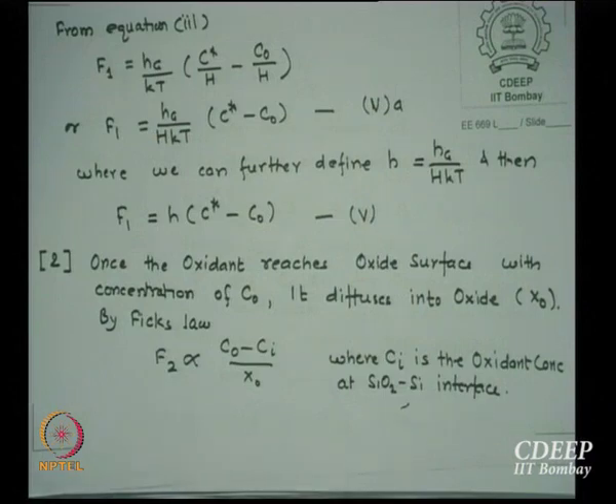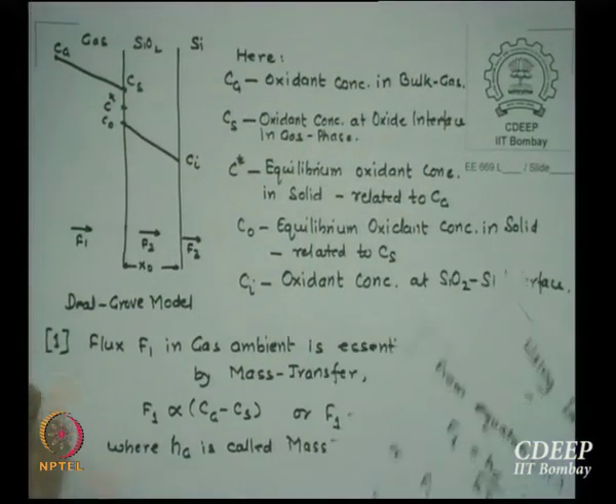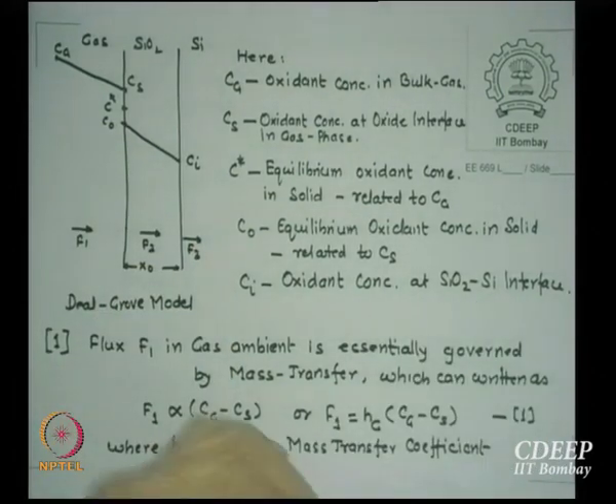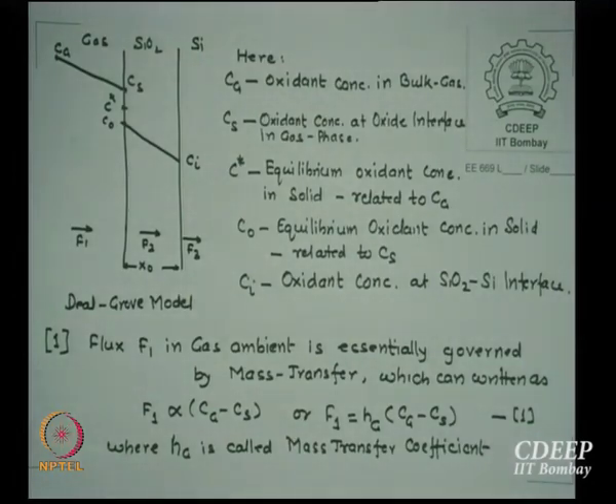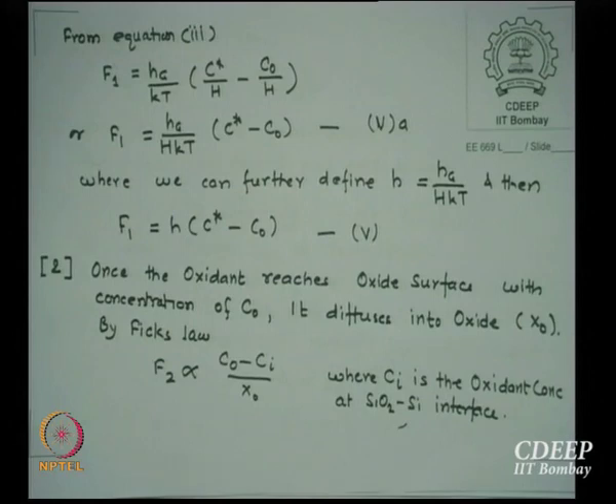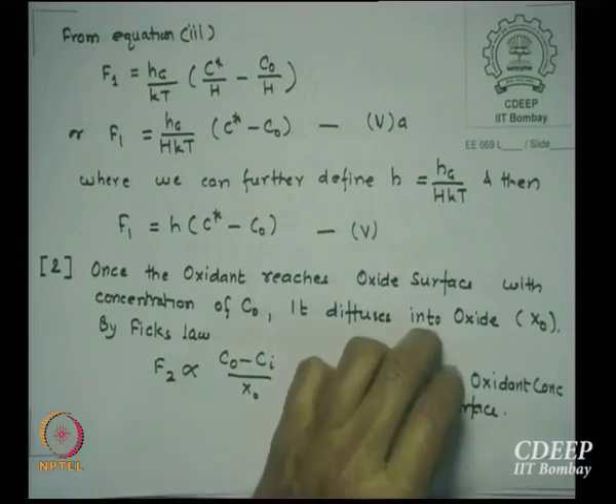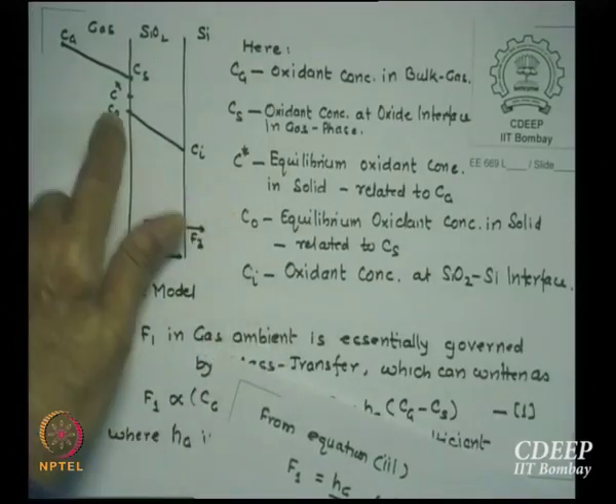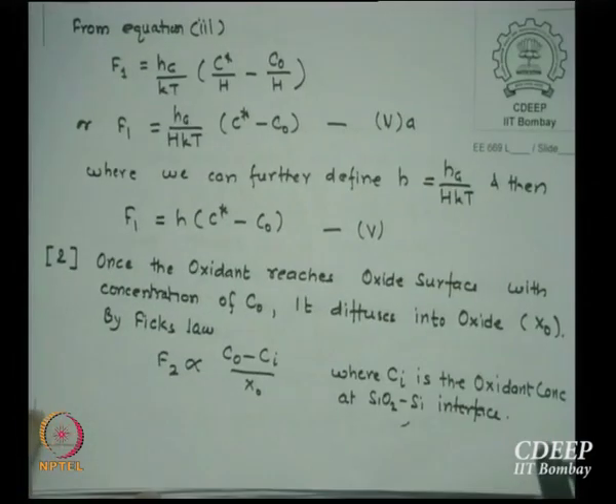Now secondly, if we look at our figure again, if you look at this figure, F1 we have found in terms of C star and C0. F2 is the flux which is diffusing inside the thin oxide, the flux of oxidant passing through the oxide thickness, and that is related to C0 minus Ci. Ci is, as I say, the concentration of oxidant at the silicon, silicon dioxide interface. So there is a gradient diffusion. So F2 is then proportional to C0 minus Ci by X0. This is essentially a gradient.